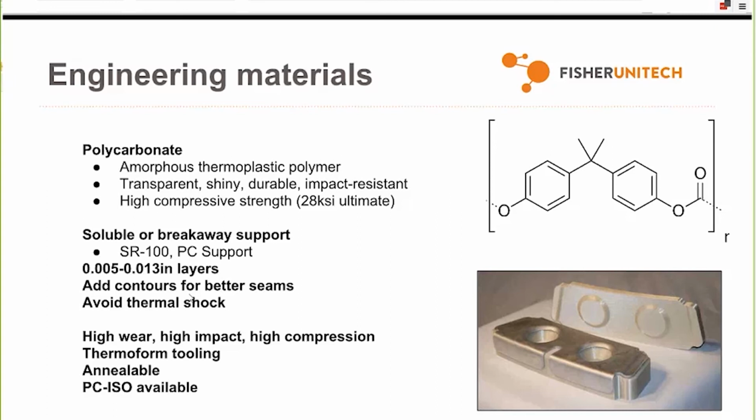It'll probably crack. Now also, sodium hydroxide, the main component of waterworks that you use to dissolve soluble support material, affects the performance of polycarbonate. So you should really try to keep soak times to 4 hours or less. Definitely don't leave it overnight.